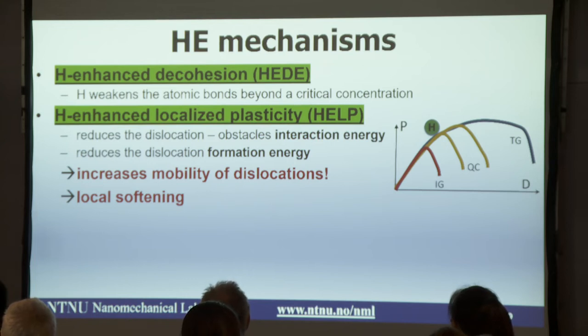The second one is called hydrogen enhanced localized plasticity. When I started to look at this one, I was confused. I mean, how could localized plasticity lead to embrittlement? The theory of HELP tells us that hydrogen will reduce the dislocation obstacles, that means grain boundaries, or the interface between the matrix and the particles, will reduce the dislocation obstacle interaction energy, or hydrogen will reduce the formation energy. If we put all this together, that means hydrogen will enhance the mobility of dislocations. In my personal understanding, maybe we can say that HELP induces a kind of local softening. So this is maybe not 100% correct.